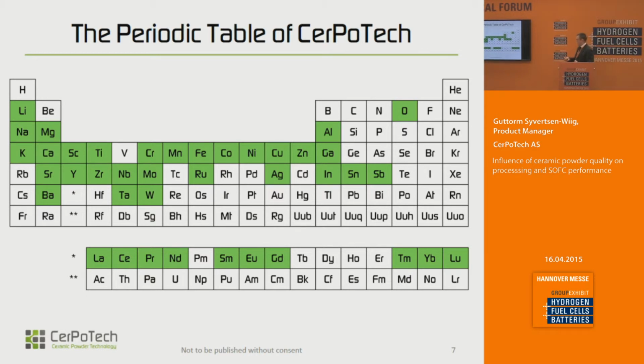So this is kind of a menu, a list of what we can work with. All the green elements here we have experience with, and can combine these into different materials. We also have some other materials we can work on, such as silicon and phosphor and bismuth, but for several reasons we have chosen not to do this, mainly because they tend to form glassy phases at high temperatures, where that might ruin our equipment. And also, for instance, silicon is not wanted in other materials such as ionic conductors.